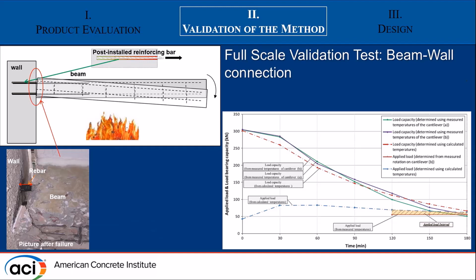The first beam collapsed after 178 minutes, and the second beam collapsed 16 minutes later, which suggests relatively good repeatability. This is in good accordance with the calculated model, which predicts a failure between 2.5 hours and 3 hours. At the end of the test, after cooling, we checked that the failure was indeed due to the slip of the rebar in the adhesively bonded spot. So that was the first test.